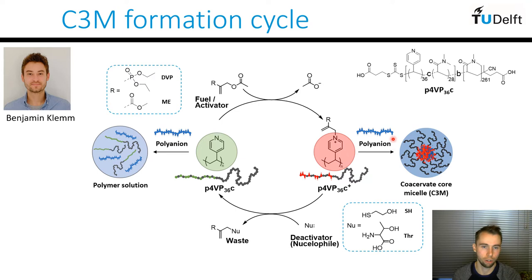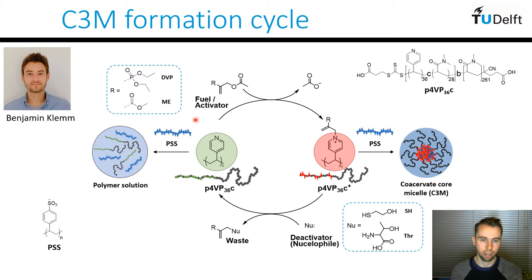For the polyanion, we're going to use a high molecular weight commercial polystyrene sulfonate of around 200 kilodaltons. In principle we could use almost any polyanion, but we chose this because we knew it formed relatively monodisperse spherical micelles with our charged polyamine.